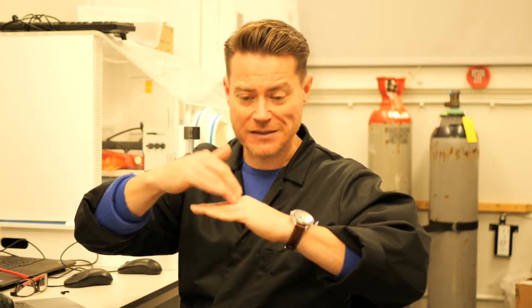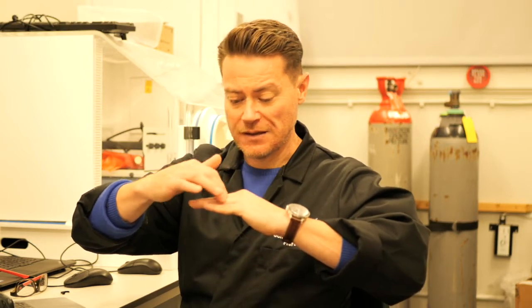Probably more importantly, you can even hold your sample under the surface of a liquid. So let's say you cover it with water, you can still bring the tip down through that water and image underneath the water. As long as you don't move the laser beam too much by refraction, you can still make the measurement under a solvent.